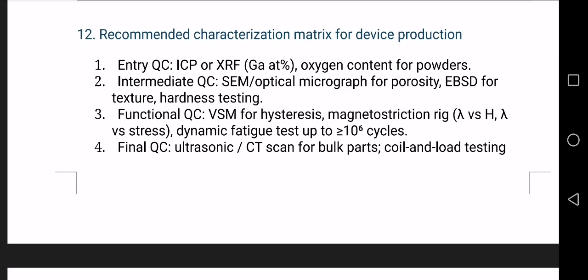Intermediate quality control during processing. It happens through microstructural inspection using optical microscopy and SEM to detect porosity, cracks, and homogeneous grains. Texture management is done using EBSD, and the fraction of 100 oriented grains and grain size distribution are checked. This directly predicts final magnetostriction performance.